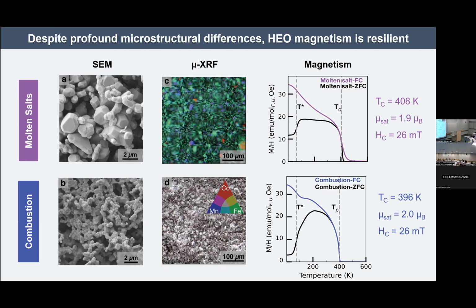While there are differences in the shapes of these magnetization curves, the overall behavior is incredibly consistent. We have TCs that vary across the series by less than 5%. The saturated moments vary by like 2%. And these 2 samples happen to have identical coercive fields. So we would say that in spite of these microstructural differences, the magnetism in these materials appears to be quite resilient, which I think is very surprising for a material as complex as this.